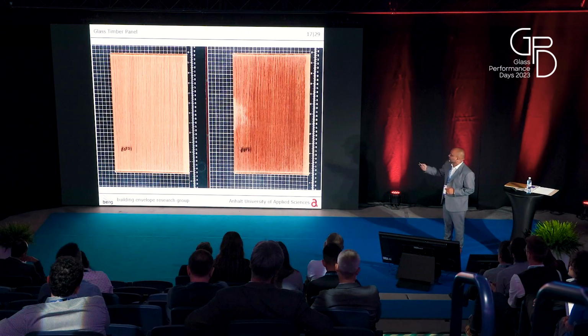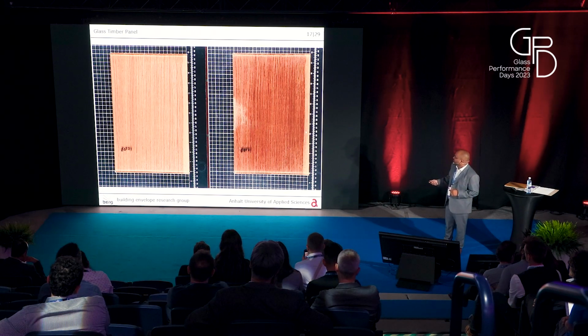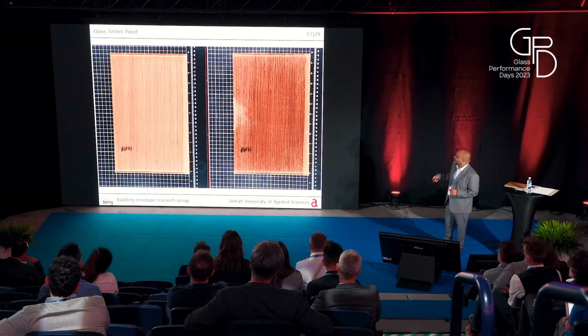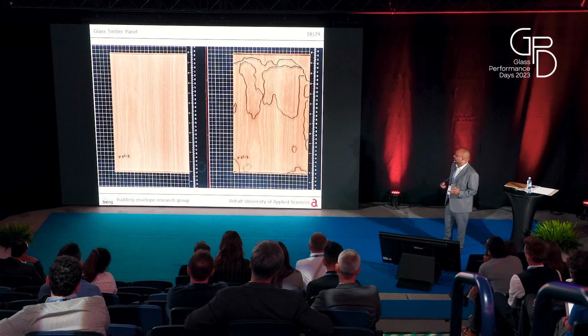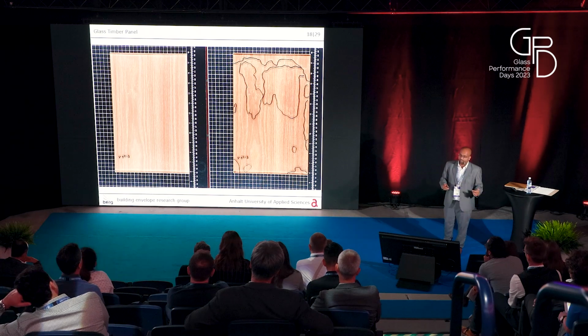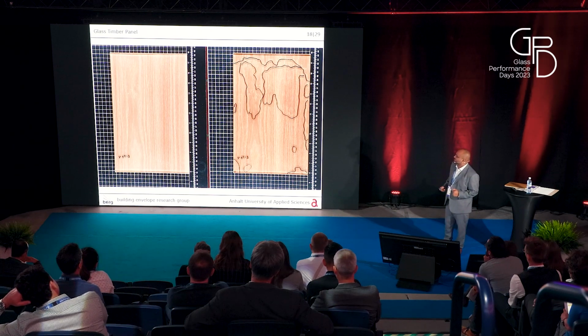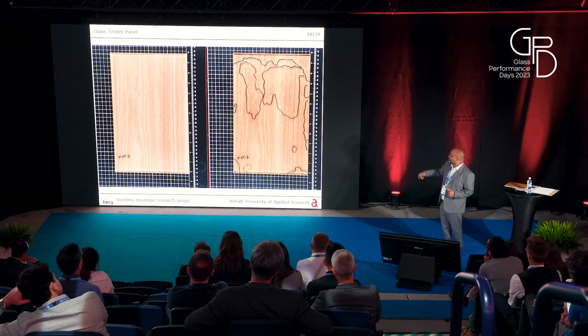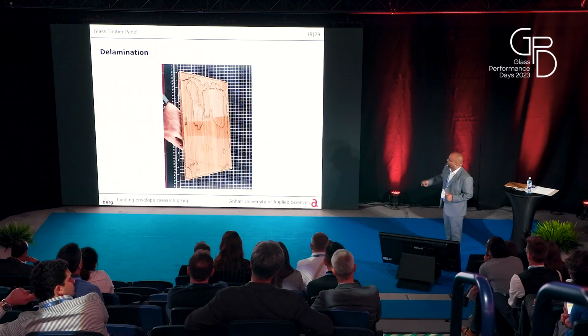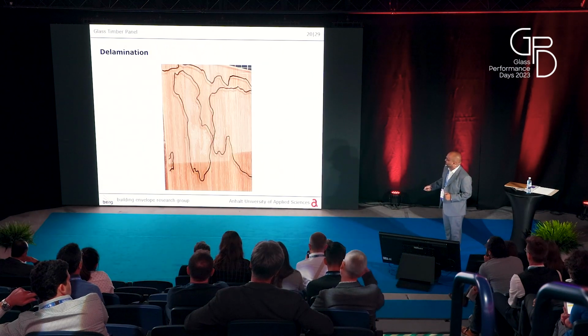I'll show you some examples. This is a before and after. There's no delamination for this specimen, but you see the deterioration of the wood. But that was not our main motive. We just wanted to see the delamination. So this is an example of delamination. One cannot see it perpendicularly, but when bent around, you can actually see the delamination.